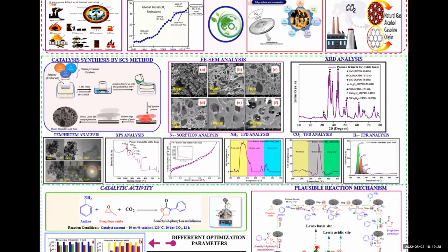In the SEM image, I see there are different sizes of pores. Yes, sir. How do you control those things? Control means these pores form in the synthesis method. When we obtain a homogeneous solution, that metal precursor solution, once it contacts the heat, at 300 degrees, the formation releases a large number of gases. Those gases are the main effect in the synthesis method for the porous nature.